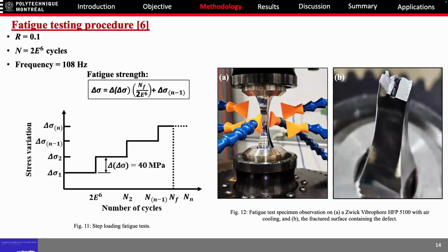On picture A, this is the actual test on the Vibrophore for one of the specimens with the artificial discontinuity. And on picture B, you can see the fracture surface with the remaining flaw all along the longitudinal axis, the weld direction.